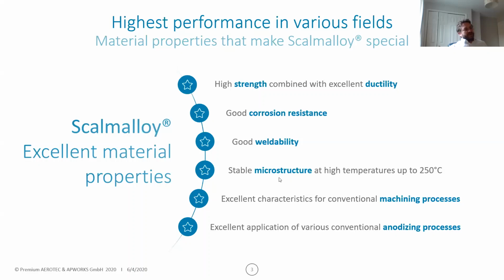So it's not a case that you see an aging effect or an ongoing aging effect in service, as you might see with aluminium silicon alloys, where you typically have to artificially age them to avoid that effect. With Scalmalloy, we do one heat treatment process, which effectively achieves a full strengthening, and there's no subsequent aging at exposure to temperature. And that's obviously important if you want reliable material properties in service, where you're seeing any kind of elevated temperature. And with some aluminium alloys, you can even get aging at room temperature.